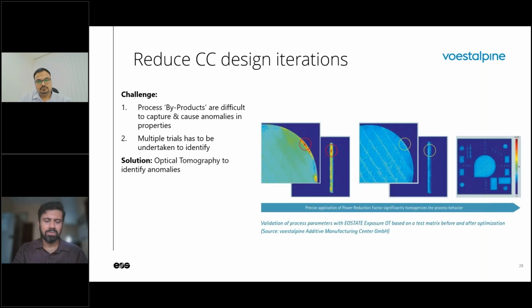And what solutions that we offered was, instead of having to print it, to process it after printing, we can directly check it whether there any anomaly, the process related anomalies that happen, such that the geometry is spoiled or not. What we do is we put a camera inside the machine and then understand whether the reflected irradiation are within the thresholds or not. I'll come to the next slide where you see how it works.